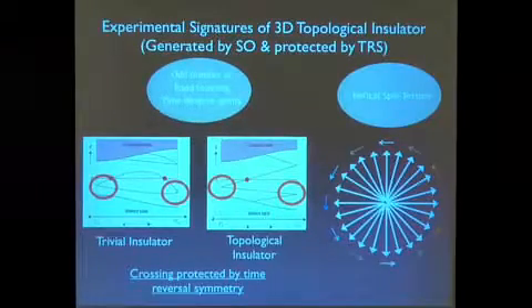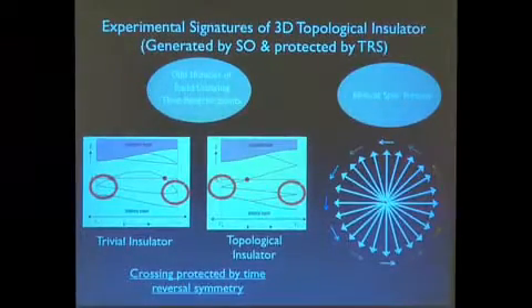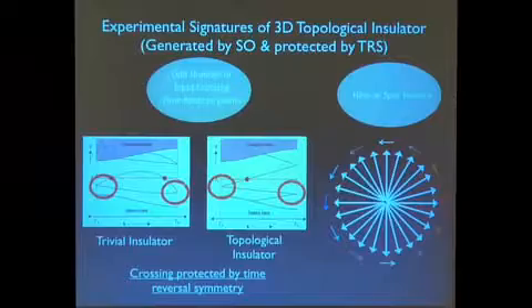The one that has its surface states arranged such that you can place the chemical potential to avoid them, or you can connect them in this way and gap them by some sort of perturbation, is the one that is trivial. These guys will have to be protected because these points cannot be avoided, if you like. For that reason, when you cross the chemical potential through this band gap, you always cross these surface energy states, and you can never get away from them. Okay? Now, the added benefit of having generated them with spin-orbit coupling is the fact that the electron's momentum and spin are coupled together.